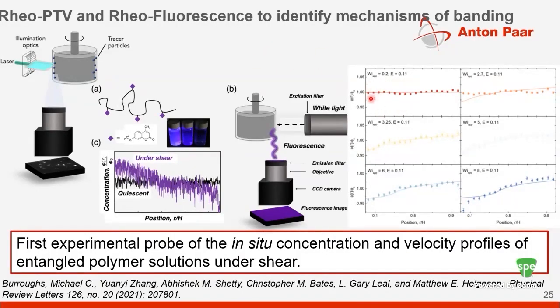Here are some concentration profiles plotted as a function of distance from the bob as you move towards the wall. At small Weissenberg numbers, the concentration is pretty flat - the y-axis is essentially a probe for concentration fluctuations. But as you increase the Weissenberg number, it moves away from that flat profile to a different profile with different concentrations close to the wall versus close to the bob. This really opens up new understanding of flow-concentration coupling in these types of systems.